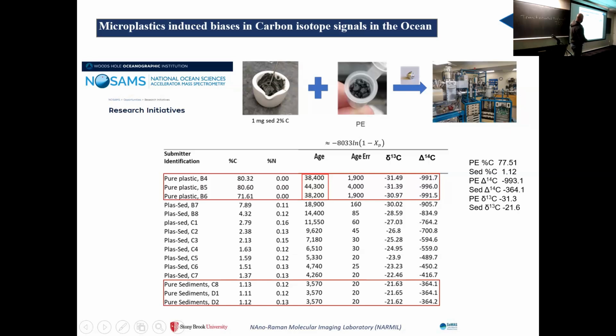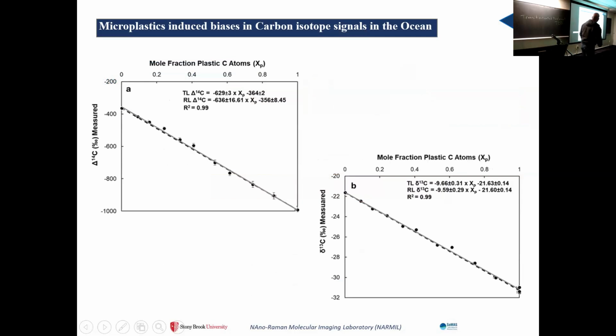So you have here pure plastic, then you add plastic to the sediment, and then you have pure sediment. We have values of polyethylene's percent carbon, the delta 13C. For example, the age of the pure plastic is around 40,000 years. The age of the sediment was around 3,000 years. So we have all this information, and with all this information, we produced these results.